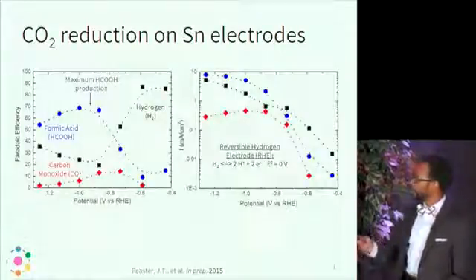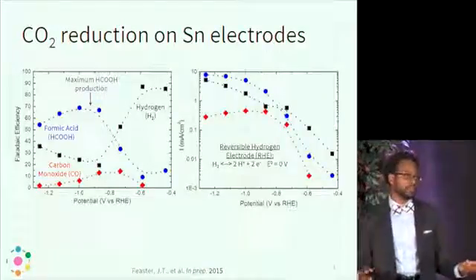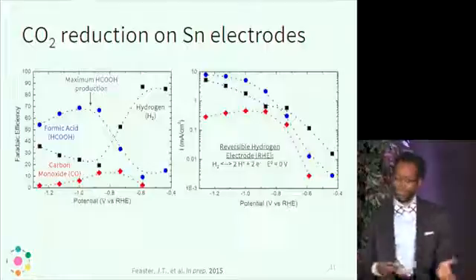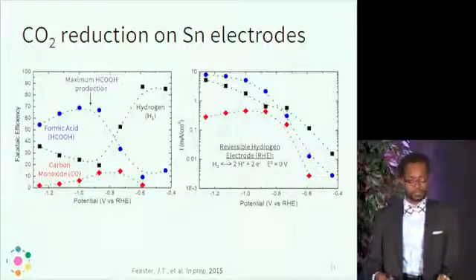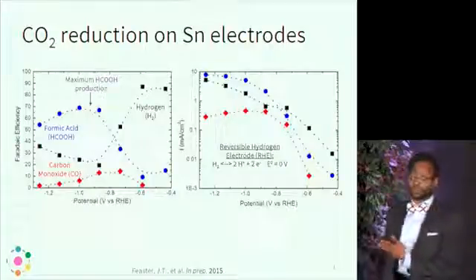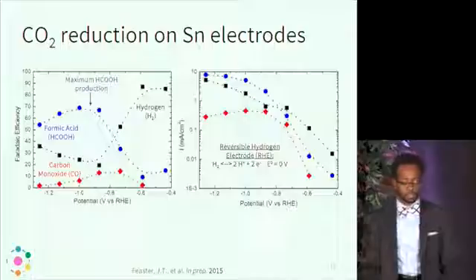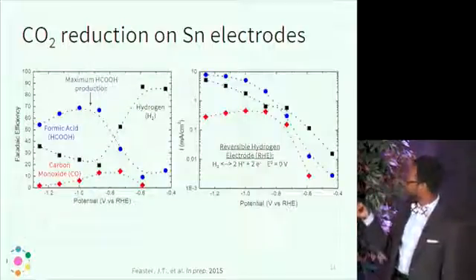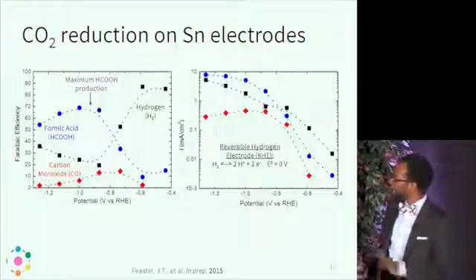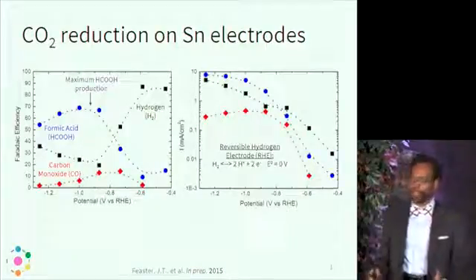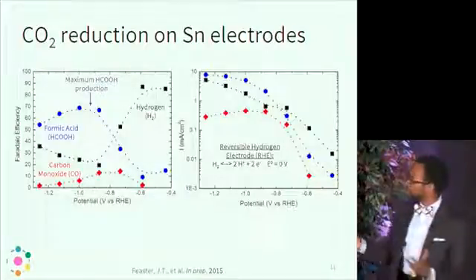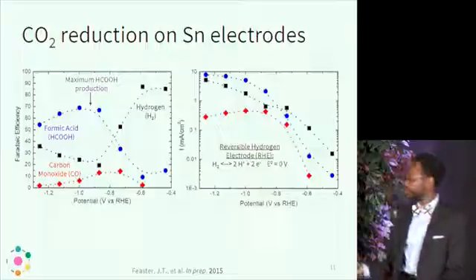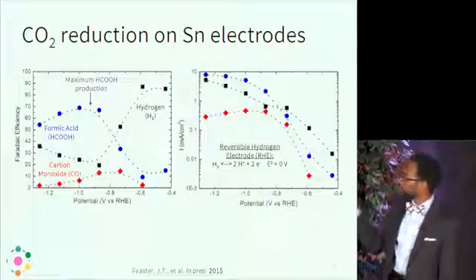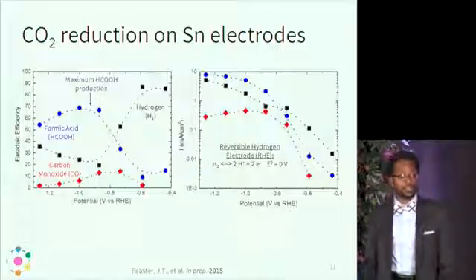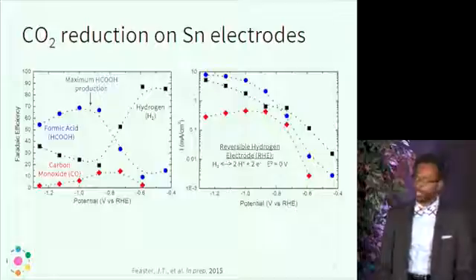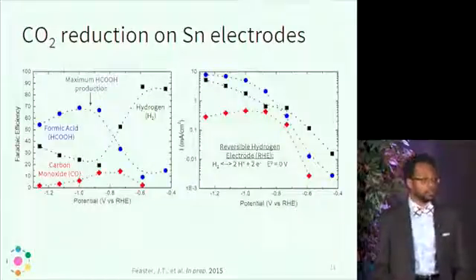As you can see here, on the plot to the left is our Faradaic efficiency, or really you can think of it as an electron efficiency, for the number of electrons that we're putting into our system versus the products that we're getting out as a function of potential. And that's being held relative to the reversible hydrogen electrode, which is just the standard metric that we use in our field. As you can see on the plot to the left, there's a maximum formic acid production right around negative 0.9 volts versus RHE on these tin electrodes. And formic acid doesn't become the major product that we observe until about negative 0.8 volts versus RHE as well. We also were able to observe a little bit of carbon monoxide being formed on the catalyst that seemed to have a maximum right around that same potential range. And all of this fits very well into what we understand tin to do for CO2 reduction.